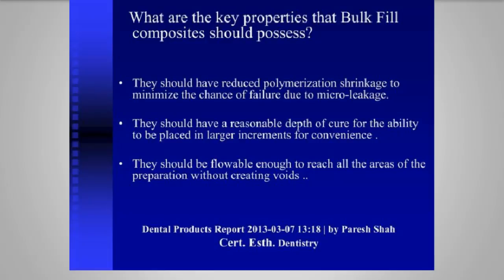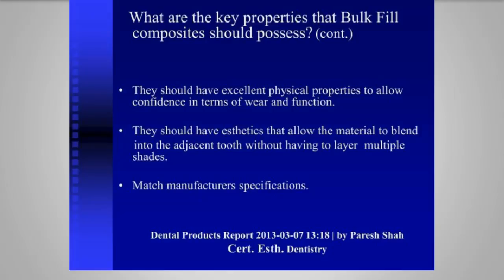Secondly, bulk fill composites should demonstrate an increased depth of cure at least to 4 millimeters, which is accomplished in part by being more translucent and having a highly translucent light sensitivity to get the light down there, so these materials can be somewhat translucent. Third, they should be more flowable to allow for easy cavity adaptation, including in the cervical margins and existing boxes. And they should be easy to dispense with minimum handling. So these are unique, and also excellent wear and physical properties.